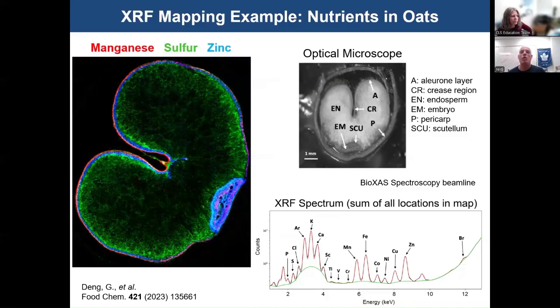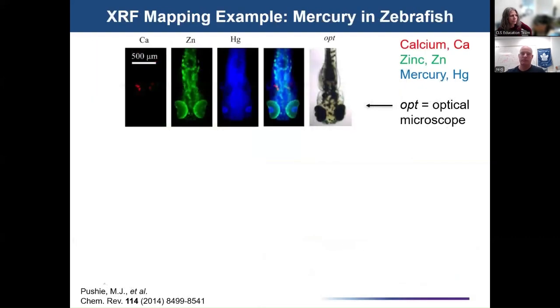But often we want to see how different elements are associated with one another on a single map. And this is what's called a tricolor plot, with 3 different elements on one map. So you can see here the manganese and the zinc form layers on the outside of the oat, while the sulfur is spread throughout the middle of the oat. And the embryo at the bottom right contains a lot of zinc, which is highlighted by the blue here.